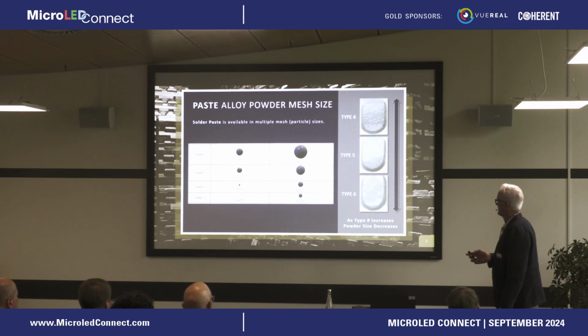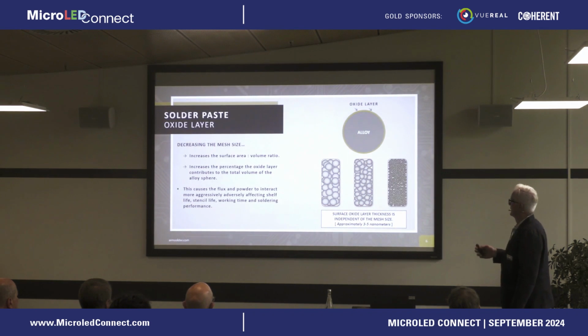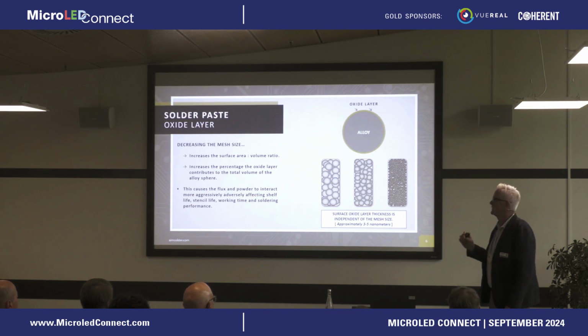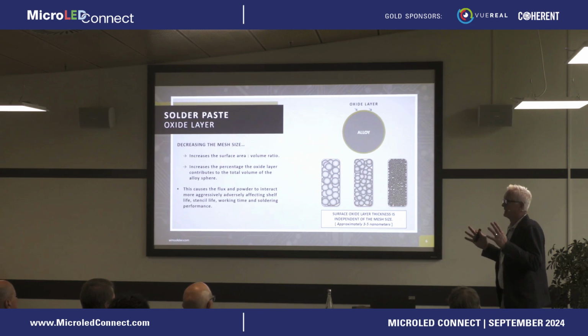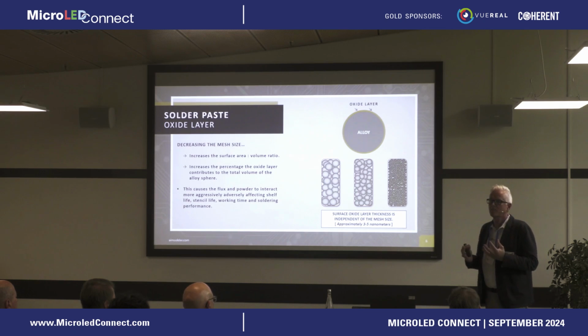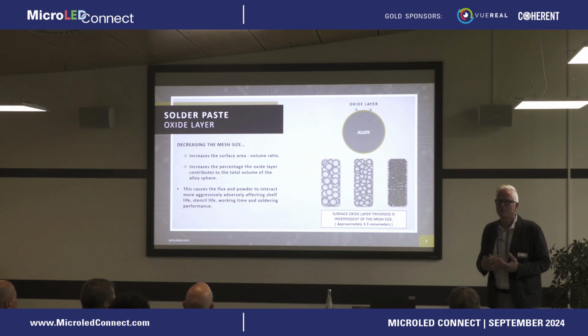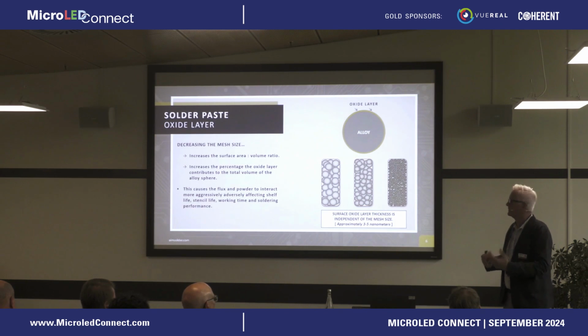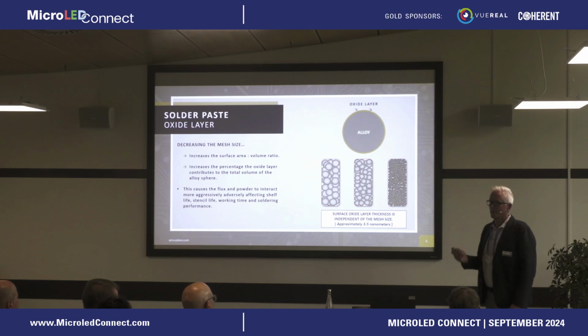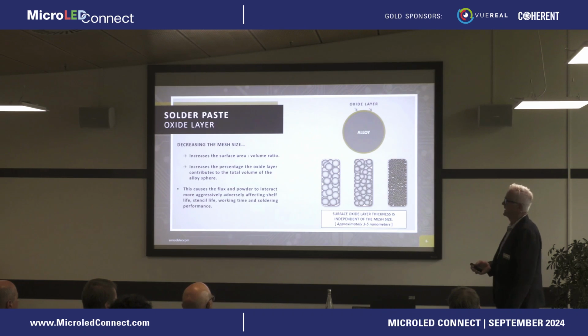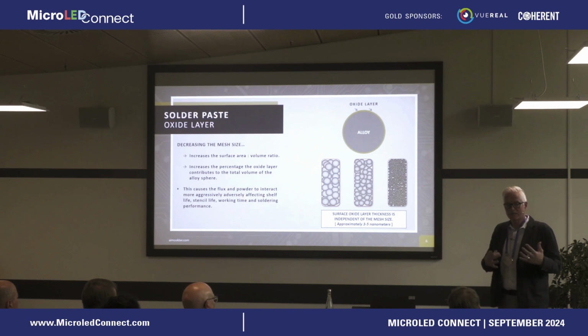As the balls get smaller, the oxide layer relative to the ball is the same. So each one of these spheres has an oxide layer that's roughly 3 to 5 nanometers. So the mass of metal can shrink, but the oxide layer will stay the same. And we need a little oxide layer on there because the oxide layer prevents the solder particles from sticking together. If you had very pure solder particles, they'd clump. So the challenge is that now I have this oxide layer that I need there for the powder to work properly. I then have to strip that oxide layer away during the reflow process using the flux medium so that the solder will coalesce into a single contiguous mass.